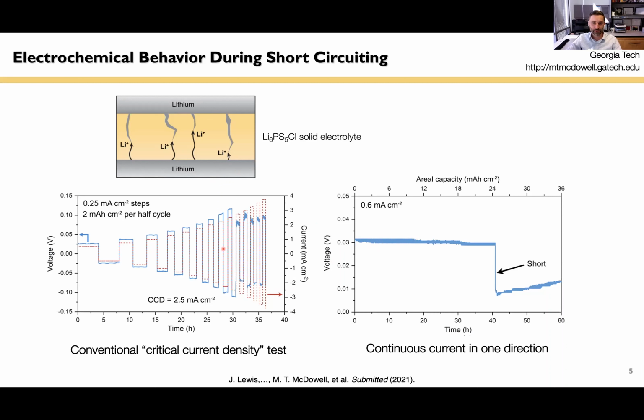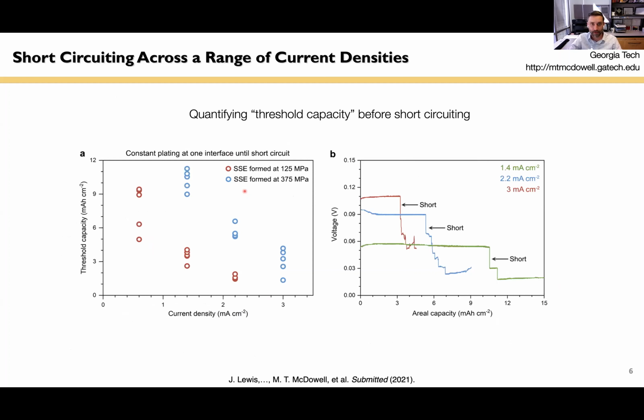So what this means is usually it's thought that these short circuits only happen at high current densities. But in fact, you can apply a low current density, 0.6 milliamps per centimeter squared, for a long period of time, and you eventually get a short circuit. And so this sort of degradation mechanism, where lithium is growing in these filamentary ways to short circuit a battery, is prevalent across all sorts of different current densities. And so it's a big problem. And so again, I'm just emphasizing the electrochemical measurement of these sorts of degradation behaviors.